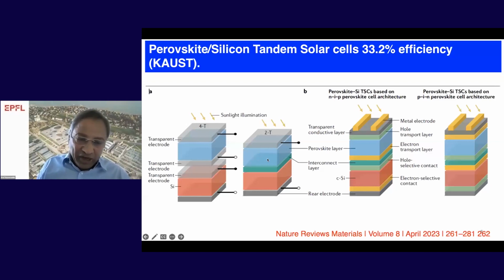configuration, the band gap has to be 1.7, and the 1.7 band gap has to be optimized with the bromide and iodide composition. Eventually, the halides segregate, and segregated halides have a disadvantage in the two terminal configuration. To avoid this segregation and the voltage losses, the four terminal configuration is more interesting. So these are very interesting research topics.